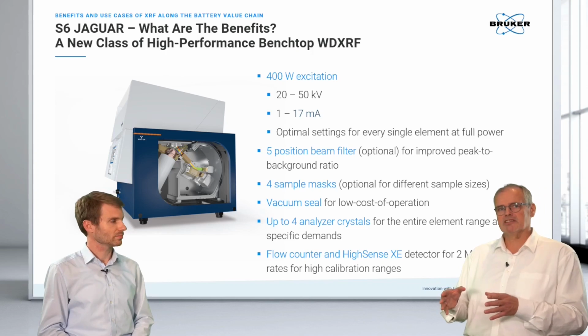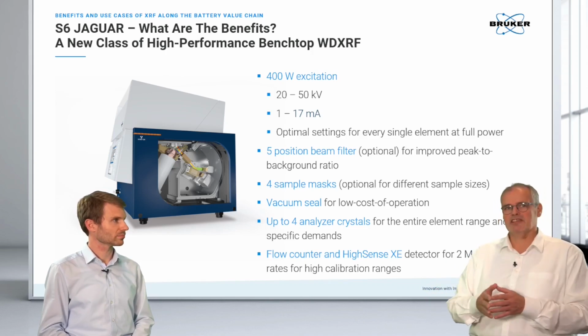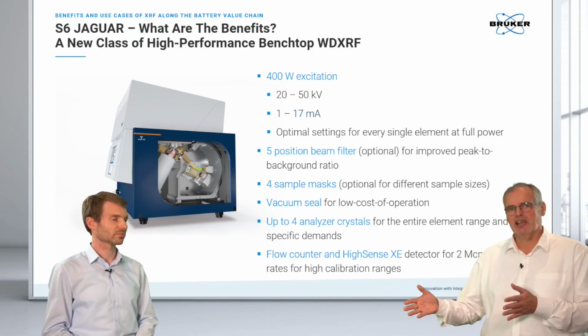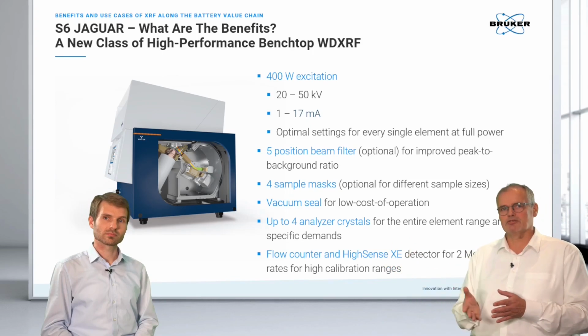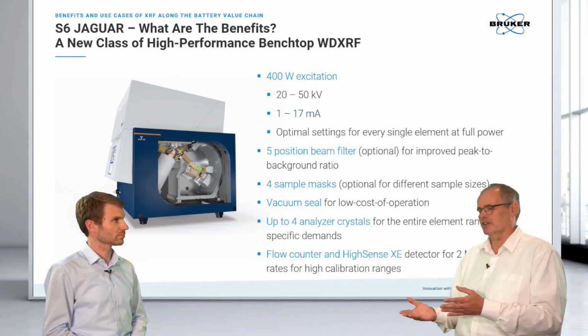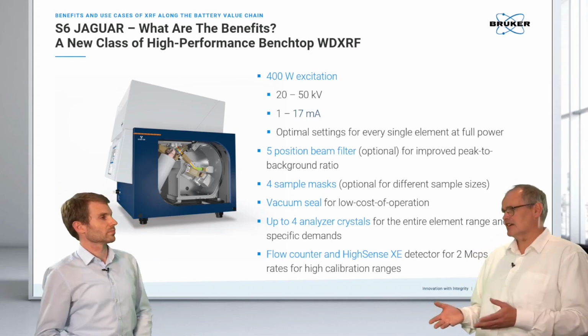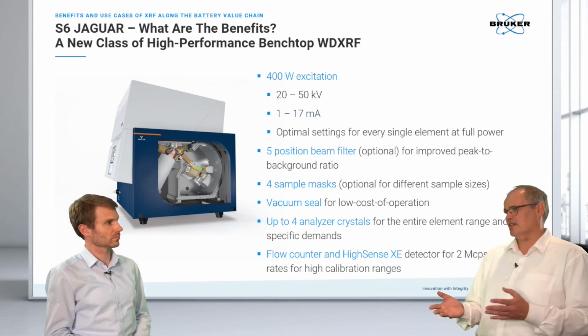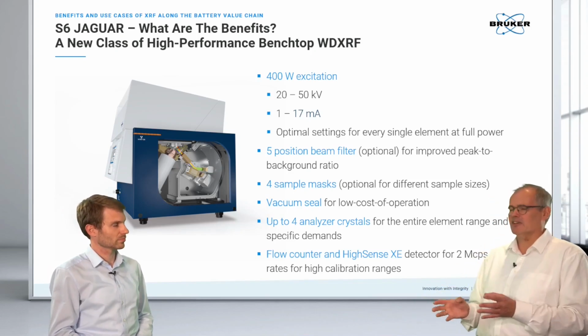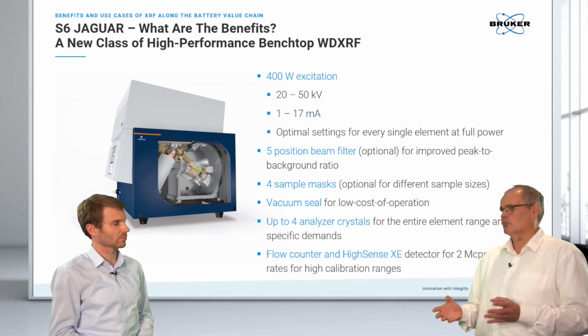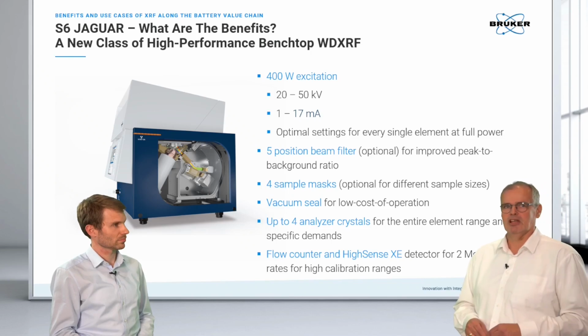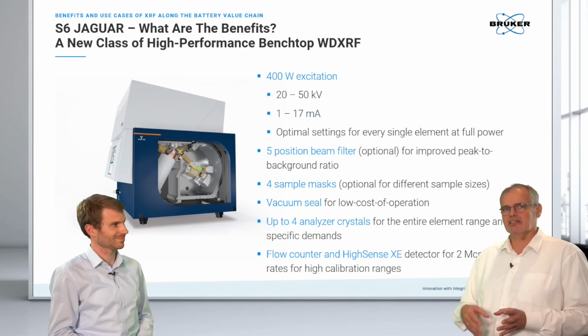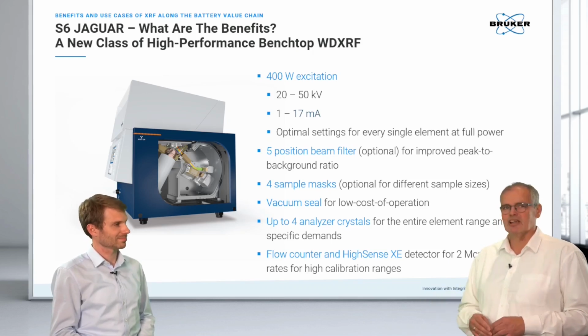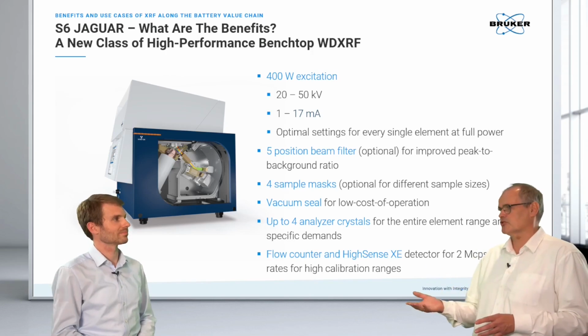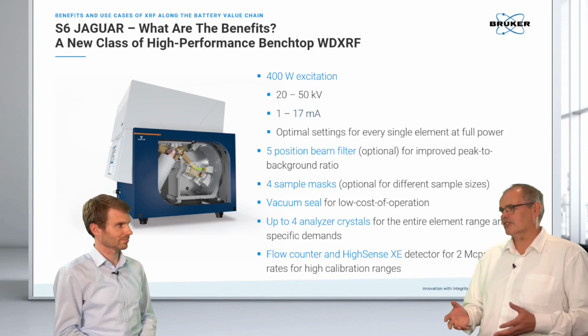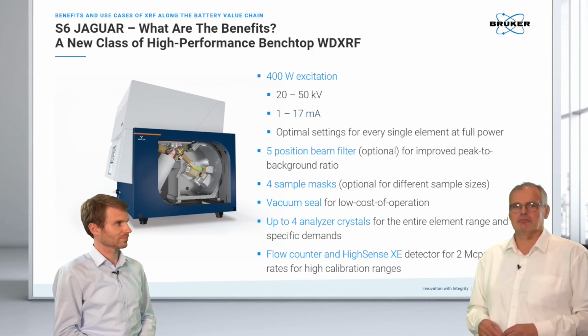So what happens here is that we have analyzer crystals which are separating the incoming beam into the different energies. And then we have two detectors which travel to the position where this energy needs to be recorded. And with the flexibility in the excitation voltage from 20 to 50 kV and 1 to 17 milliamps, we can fine-tune the excitation and the detection of each element, which then leads to a very nice analytical power. So this sounds a little bit complicated, but the instrument does the setting by itself. It knows which crystal to use and to which position to travel. So this is all automated. The only thing we need to do is to tell it, hey, those are the elements I'm interested in.